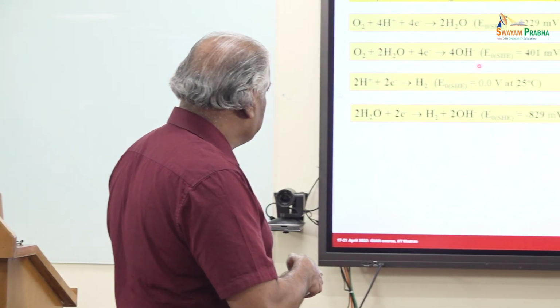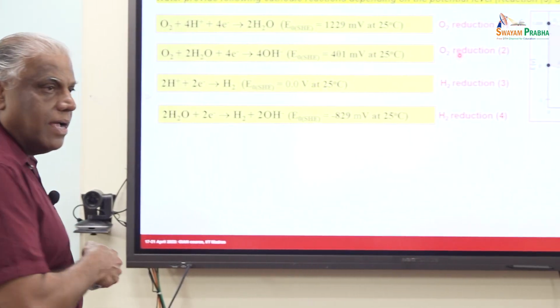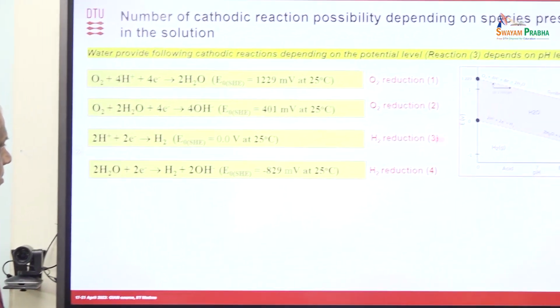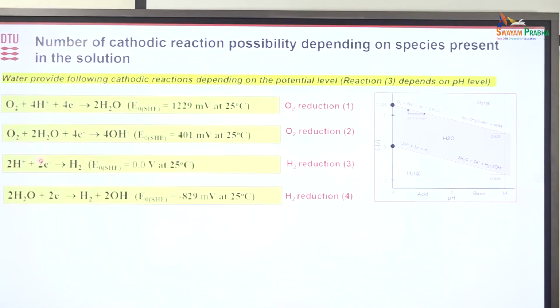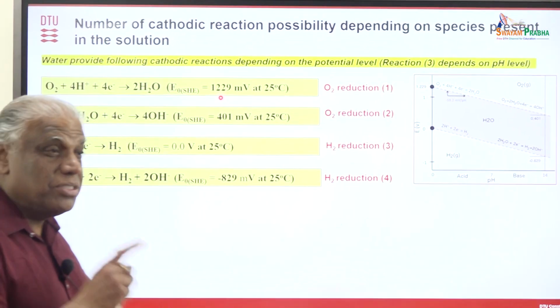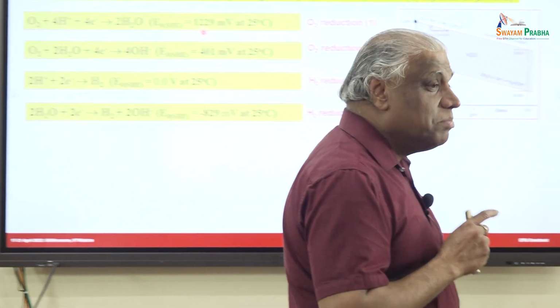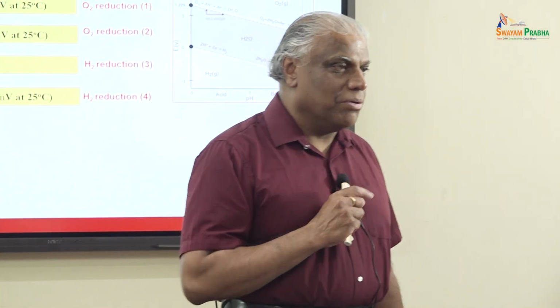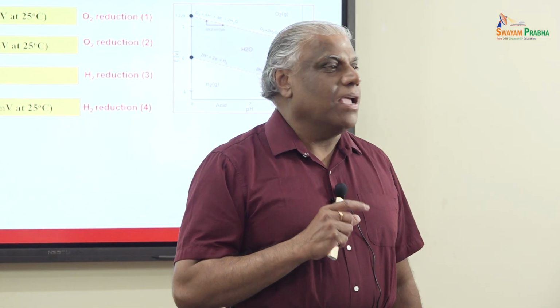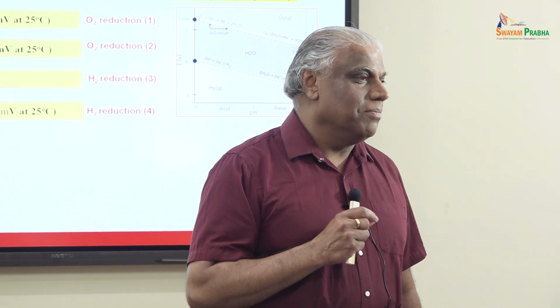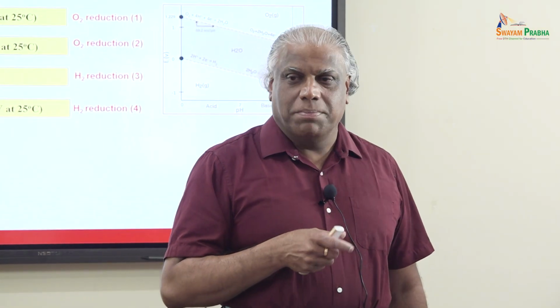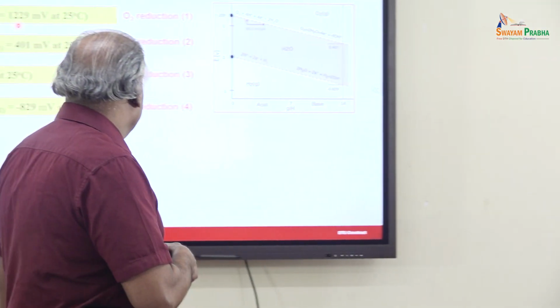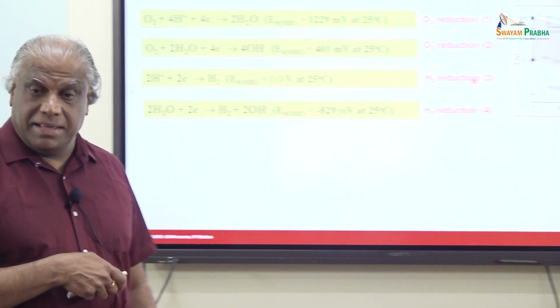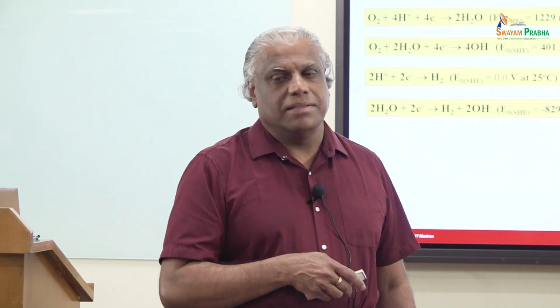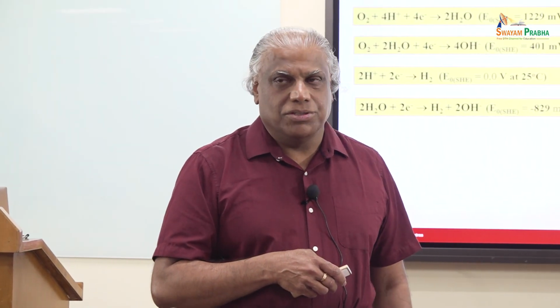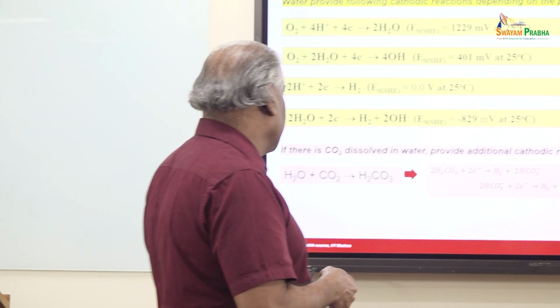This reduction reaction, especially this reaction, is more important, and that reaction can take place around this pH value. So that is the importance of that one. Oxygen is a very important species in relation to normal corrosion issues, and that's the reason everybody wants to remove oxygen from the system. If oxygen is removed, you are removing the cathode species, because hydrogen is inherently less available in neutral pH conditions. You will see that later. So oxygen is an important thing in this case.